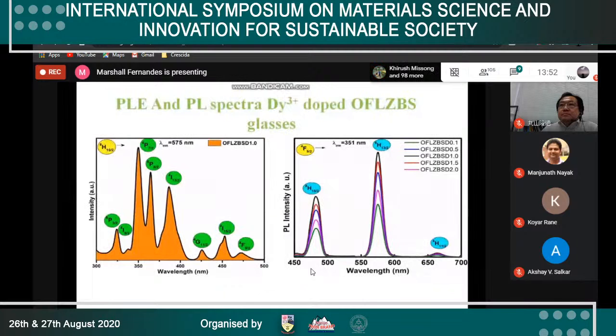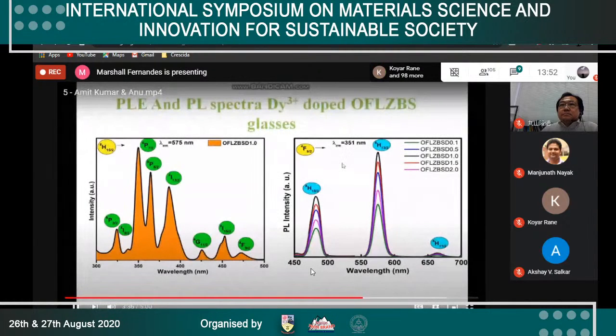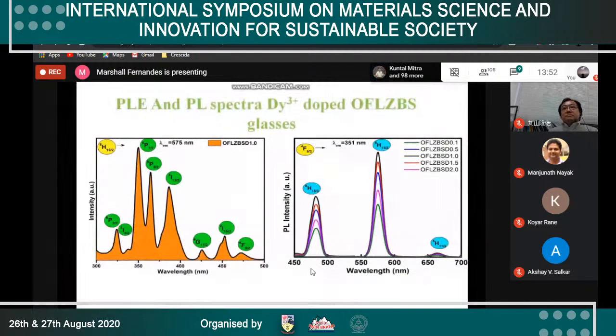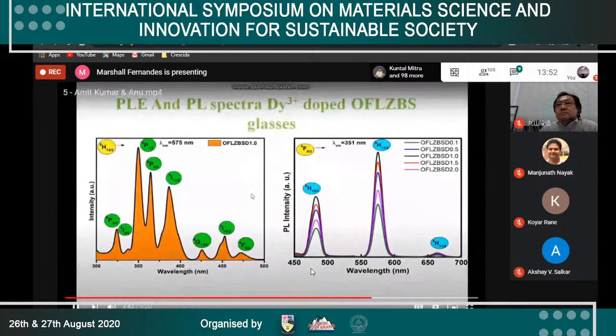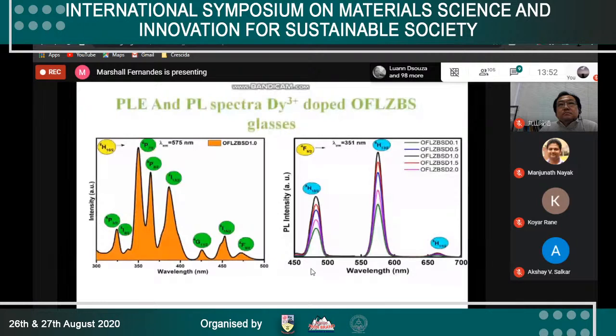In emission spectra, we get two intense peaks at 486 and 575 nanometers, and a weak peak at 665 nanometers, corresponding to blue, yellow and red emission respectively. The intensities of these emission bands depend upon the concentration of dysprosium ions. The decay profiles of various glasses are shown here.